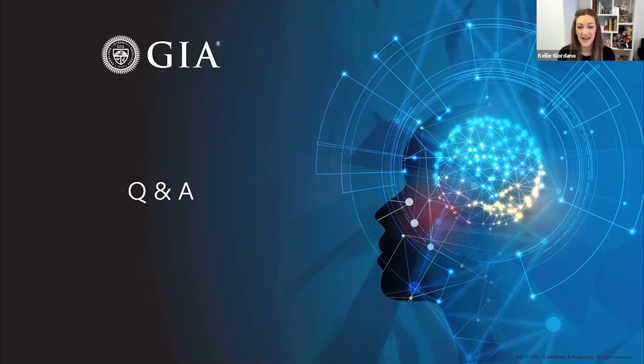Okay. And last one, can a powerful microscope, like an electron microscope, let us actually see the carbon atoms and if there are any defects? Well, yes, with a really excellent TEM, transmission electron microscope, technically we can see atoms. I'm not sure we can see one defect at that resolution in the TEM, but that means we need to damage the sample. The sample has to be fabricated to a very thin, very tiny sample before we can put it into the TEM. So that is a method for research to see the atoms in a crystal, but in the gem lab for identification purposes, that is prohibitively expensive and also not applicable technology for gem material because we cannot damage any of our gemstones.